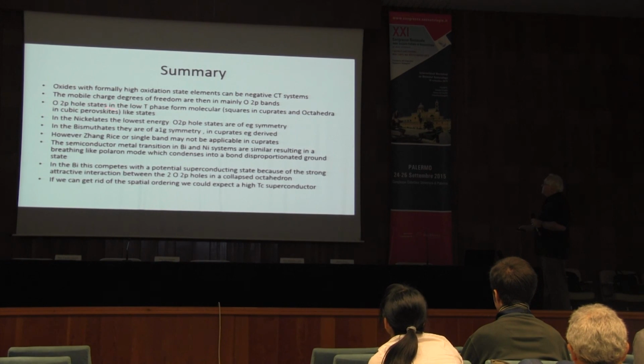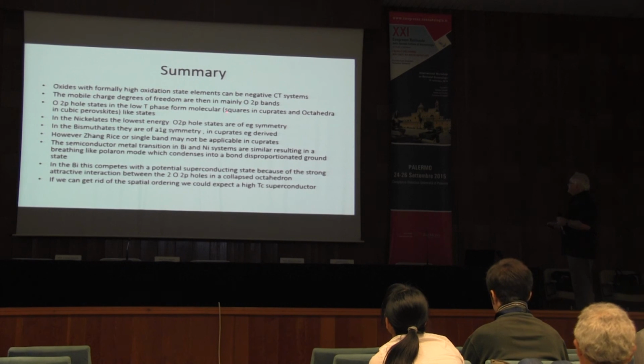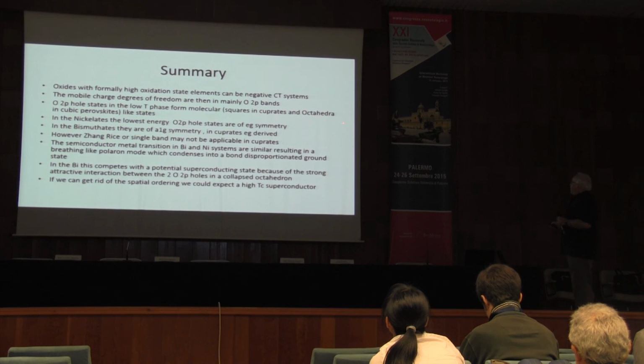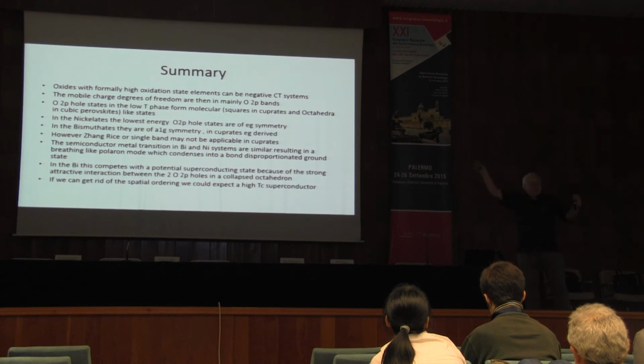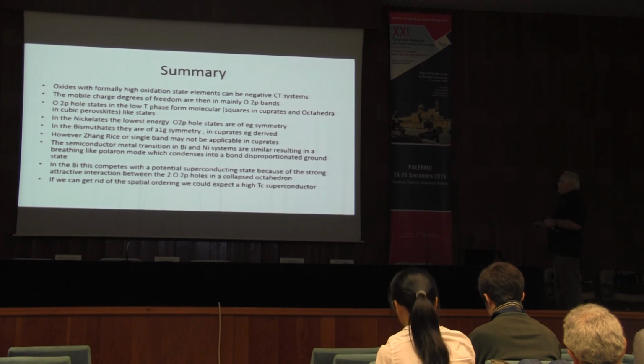The O2p hole states in the low temperature phase form molecular orbitals. These are squares of x squared minus y squared symmetry in cuprates, and octahedra in cubic perovskites. And these holes in the octahedra, you then have to think of that as being a new element, you might say, and that has periodicity, which will give you a band structure, but that's why those band widths are so narrow. The width of this large object actually has only a few lengths, or one length in each direction.